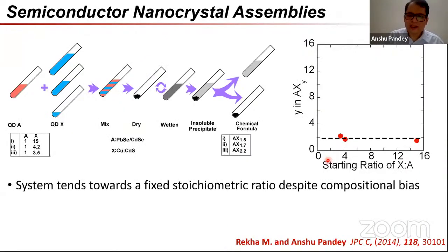There's a stronger indicator of long-range order, which is the existence of stoichiometry in this system. What do I mean by stoichiometry? I mean something like this. You mix up these charge transferring nanocrystals, which have some engineered states, in random ratios. So for example, over here, I'm varying the ratio of quantum dot x from 3.5 to 15, and then proceeding with allowing them to transfer charge.